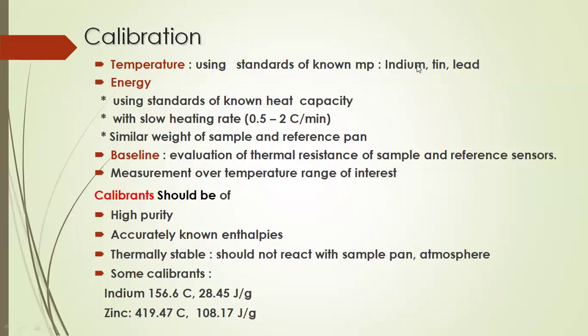So you take these calibrants supplied by your vendor, which are of high purity, for which the enthalpies are known, and which are highly thermally stable. They do not react with your sample pan, and they do not react with the atmosphere. Take a small weight of your indium or lead, depending on your operating range. Run the samples at a lower heating rate, let's say 0.5 or 2 degrees centigrade per minute, and find out its delta H and melting temperature. If it is within the reported range of your material, you can say that your DSC is calibrated.